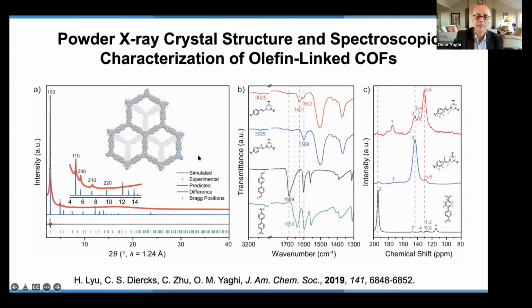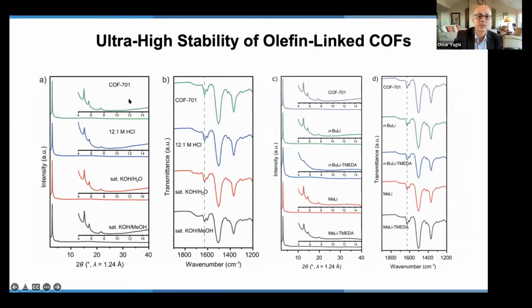But more importantly, we find that this structure is extremely stable in strong acid and strong base. You see the X-ray powder diffraction, the crystallinity is maintained, the structure is maintained. We check that from X-ray powder diffraction as well as by IR. And you see here even corrosive materials like butyllithium do not affect this material. And that's what you would expect from a carbon-carbon bonded backbone and a carbon-nitrogen double bonded backbone.